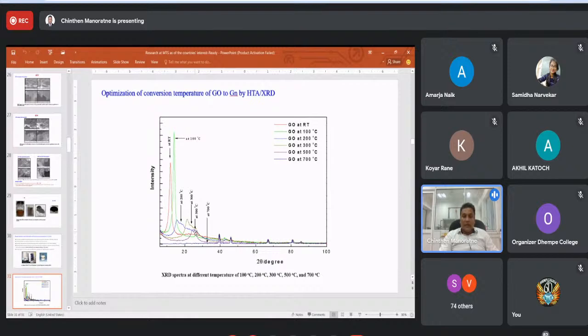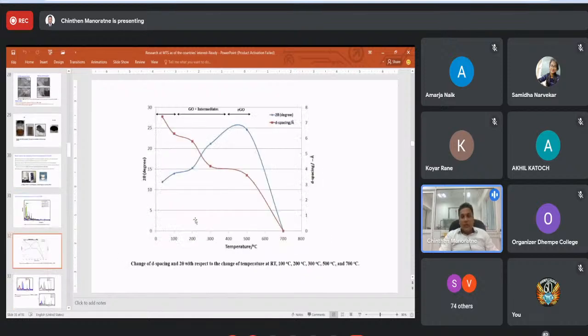So we found that the graphite oxide to graphene conversion takes place at about 500 degrees centigrade. This is the corresponding d-spacing change and 2 theta change. You can see that graphite oxide converts to graphene through an intermediate structure.